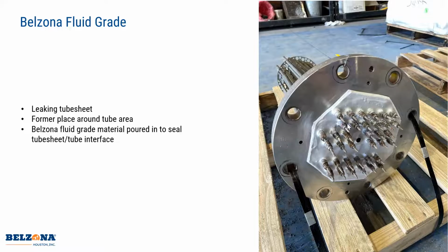So we came up with a plan to use our fluid grade material. We have a lot of fluid grade materials that can be applied thick, so they have no thickness limit. They're very cohesively strong. So we created a former around this tube sheet and poured it in about an 1/8 inch thick to really cover that interface, and it worked great.